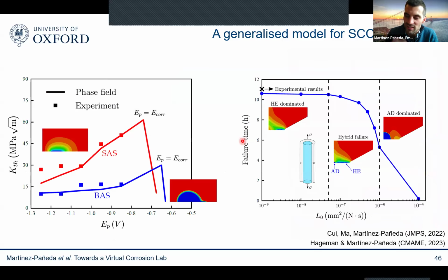But also, what this means is that at the end of the day, you have a model that without any assumptions, just providing the model with the material, the environment, and the loading conditions, can capture the failure. And you can see here that it agrees pretty well with experiments over a very wide regime, all the way from the cathodic regime where hydrogen dominates to the anodic dissolution regime.